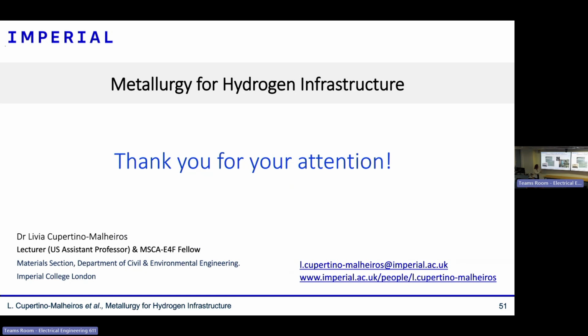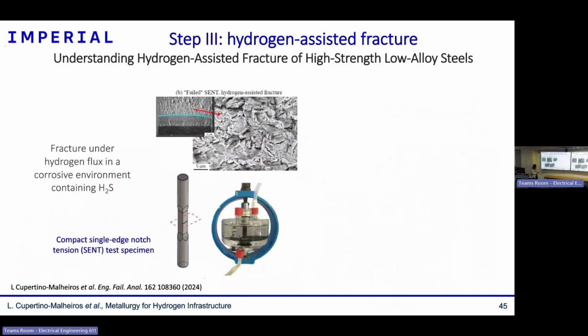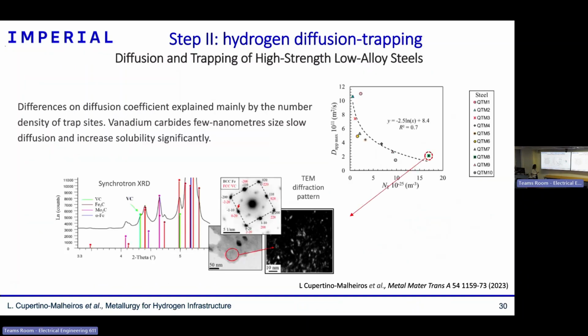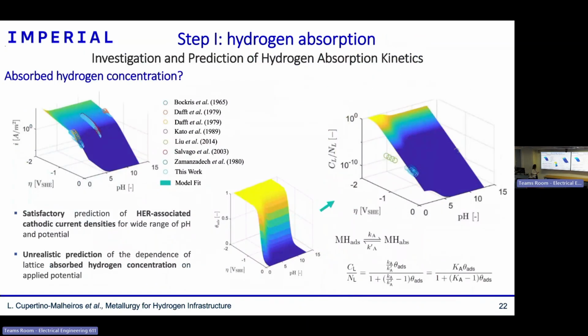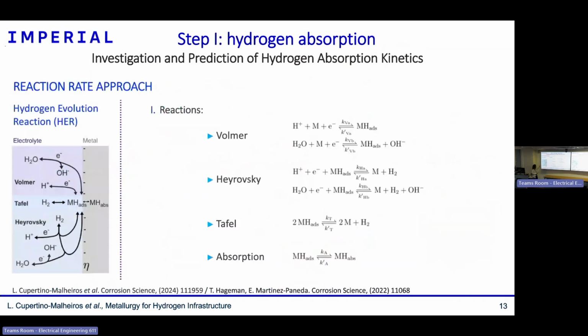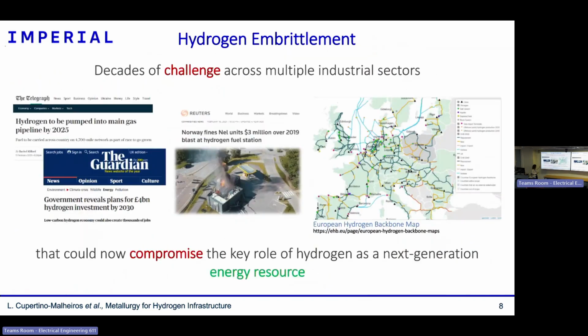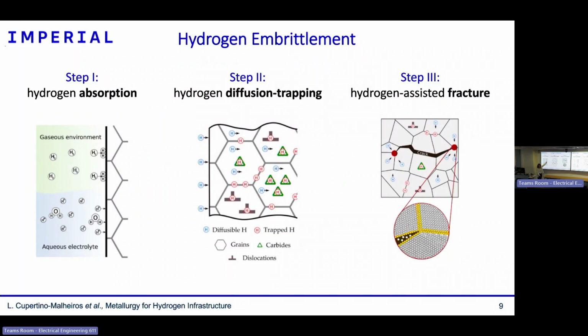No, not really. So yeah, I went quite fast, but I think if I go back to the scheme, maybe even the first one. What enters the steel is actually the hydrogen atom. So in the case of a gaseous environment, that involves the dissociation of the H2 gas on the metal surface. And then these atoms are first adsorbed at the metal surface. And then part of these adsorbed atoms at the surface get absorbed inside. And the other part will just recombine and go back.